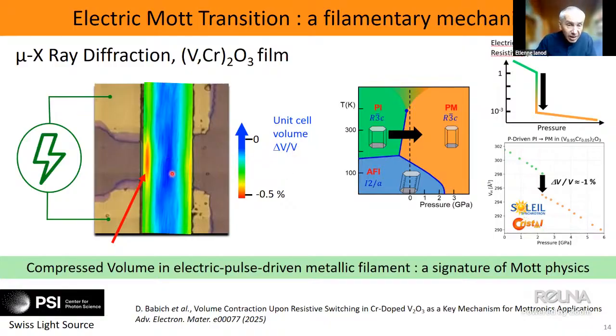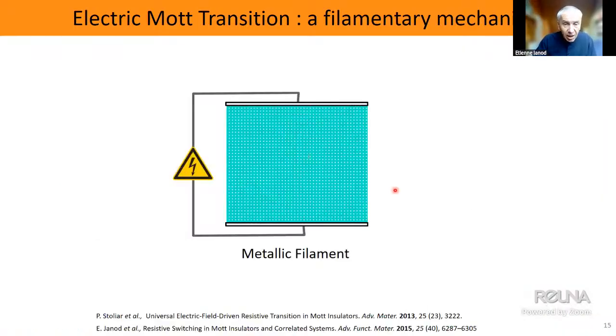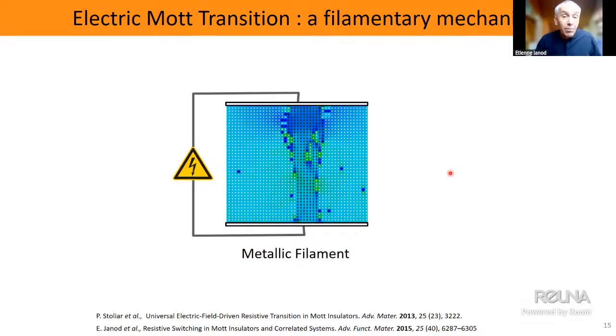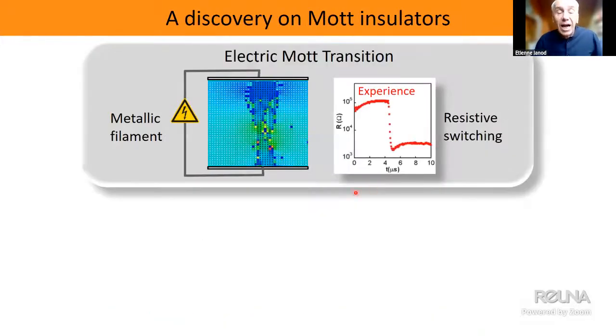In order to confirm that, we have done some simulation. I don't go into detail, but as you can see on this animation, this simulation confirms that most likely the mechanism of this insulator to metal transition occurs through the formation of a filamentary conducting path.